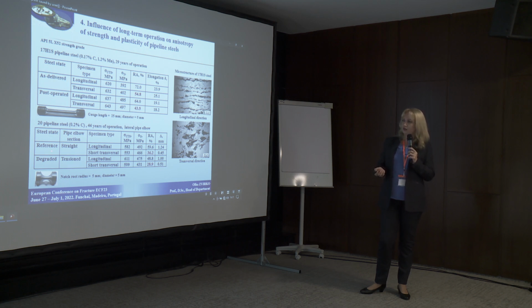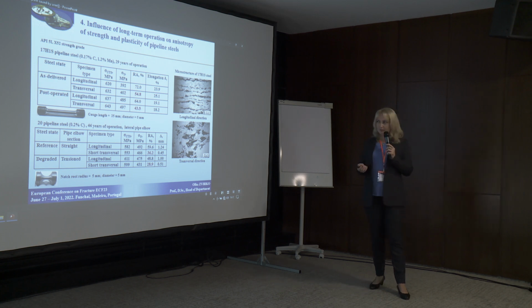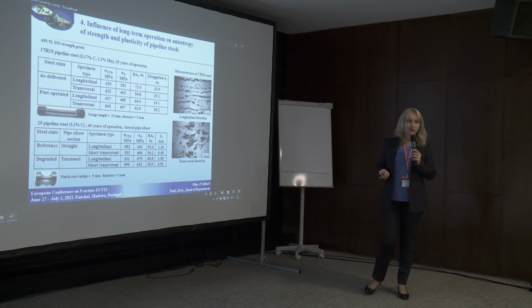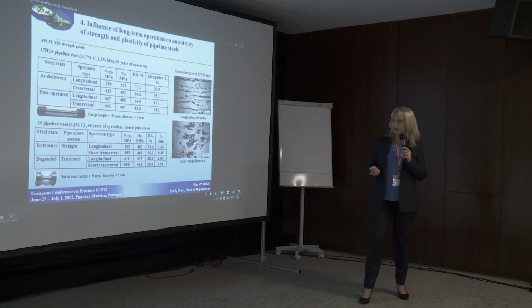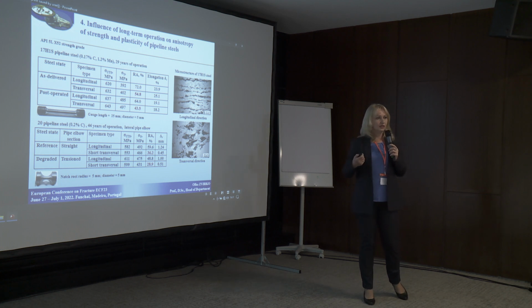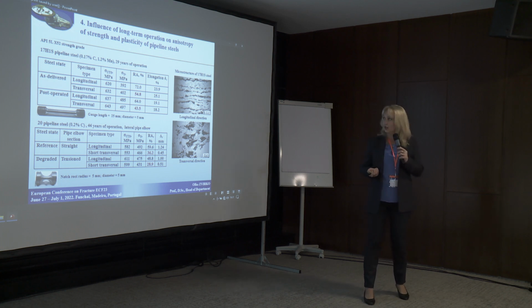Specimens were cut out in different orientations relative to the rolling direction of the pipe, and for a pipe elbow steel, the properties of the tension section were compared with the straight one, because it was suggested that the degradation degree of the tension section can be higher, based on revealed in-bulk delamination in this section.